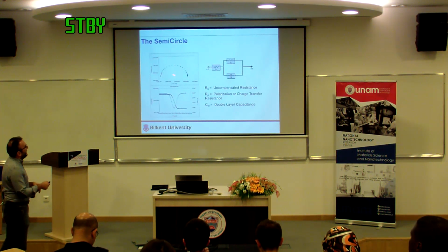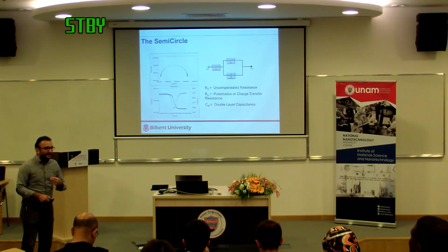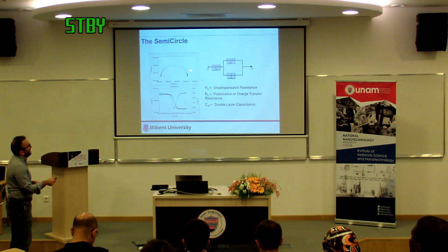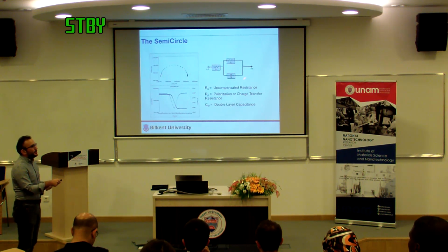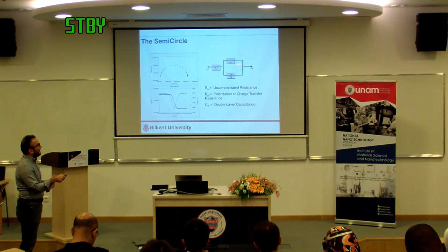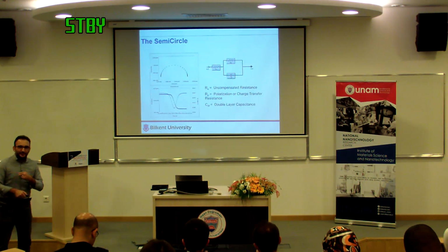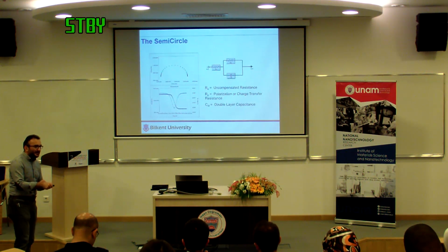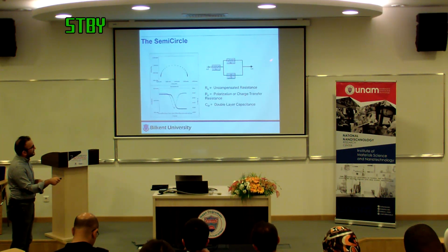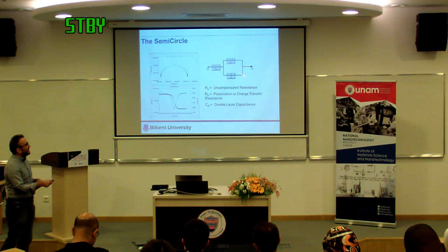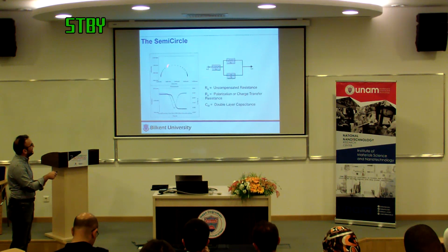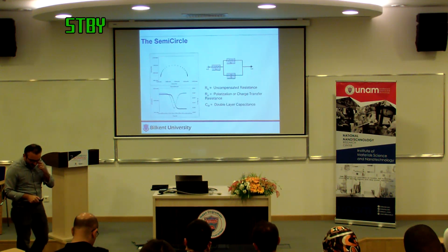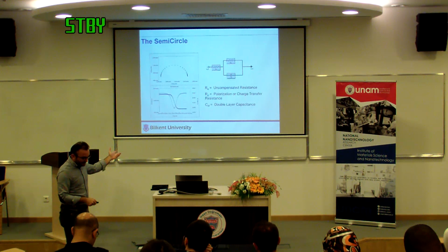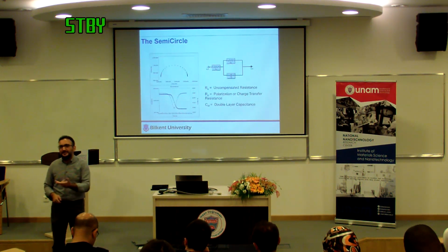So if you look at the typical semicircle, the reason there's a semicircle is because at high frequency, this capacitor is a short, so you go through this path and you only get this resistance. At low frequency, this capacitor is an open, and when that's open, you get the sum of these two resistances. And in the middle, you get something that has an imaginary component due to the capacitance, and that's this bit right here. So by doing that experiment, you can identify all three components independently from each other.